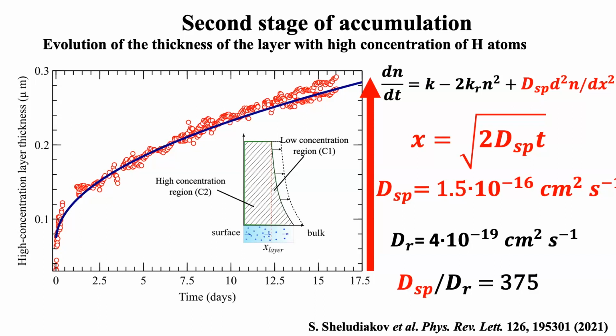So at the same experiment, we find a way to find diffusion due to recombination and diffusion due to spatial diffusion, or penetration of this high concentrated layer into the H2 film. And the ratio of this coefficient is 375. So it's faster, much faster than diffusion due to recombination.